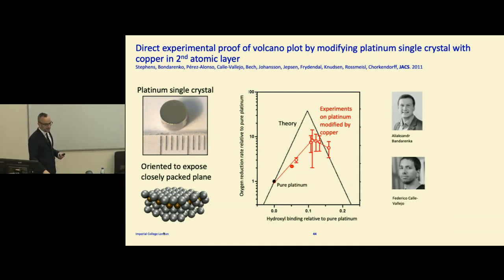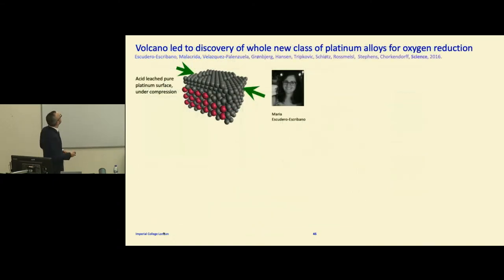So we later tried to look for other new alloys, because the problem with this alloy is you're relying on just a tiny amount of copper. That copper will leach away in the acidic environment of a fuel cell. So bulk alloys, where you have the same composition throughout the middle, would be more appropriate. Typically, we were looking at alloys of platinum and rare earth metals, lanthanides more specifically. And typically, we found they formed a very compressed platinum structure at the surface.